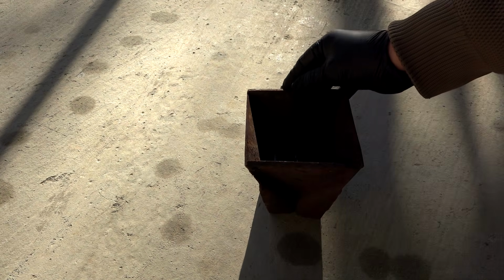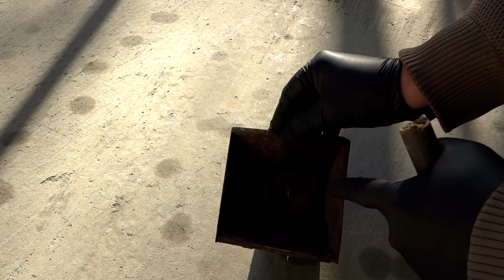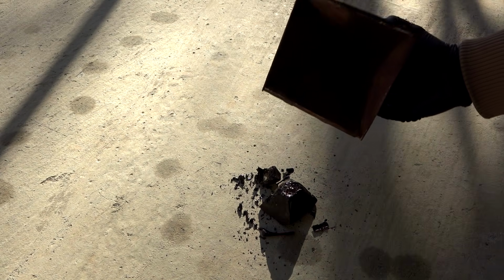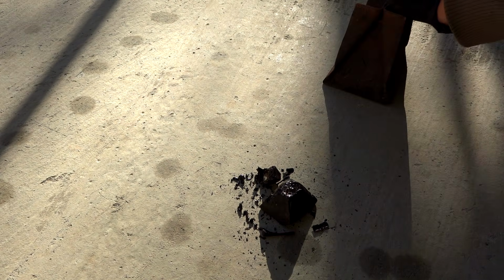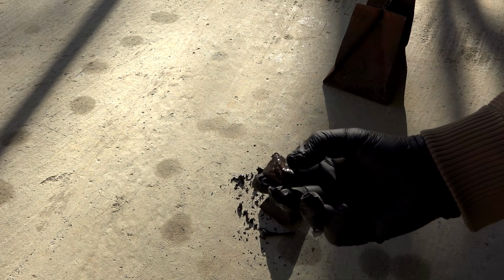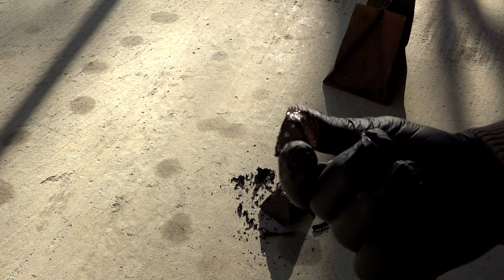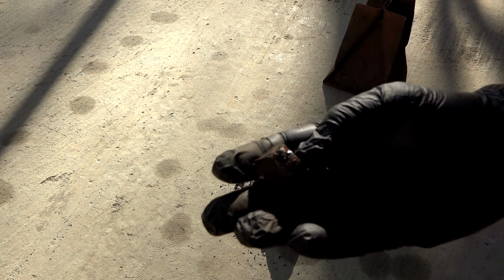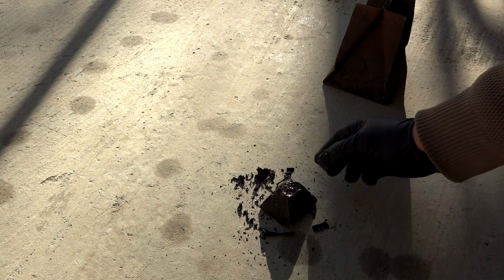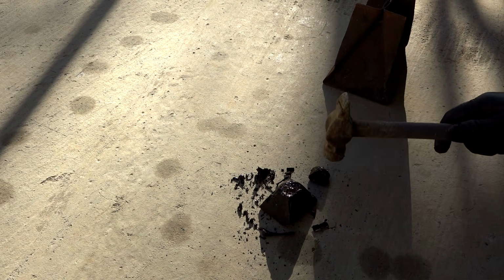The contents have cooled down and can be removed by hitting the concrete floor or using a hammer. Everything turned out perfectly. Slag is like glass. This is a sign of high-quality melting. This slag does not need to be thrown away. It can be used 2 to 3 more times to melt the next batches. I will put it away for storage.